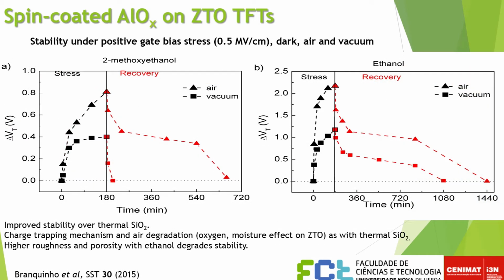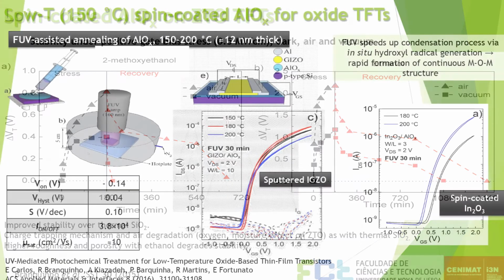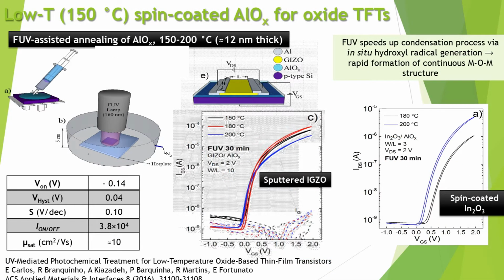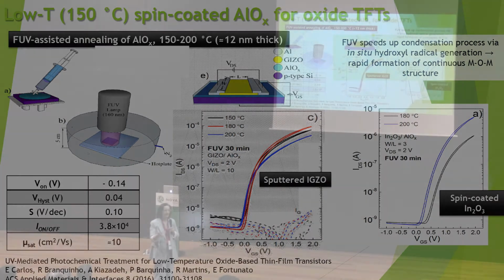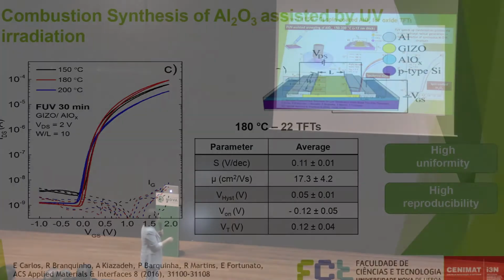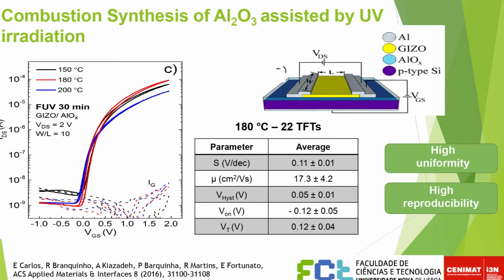And again, some stress stability with the devices, and more recently, by combining the combustion synthesis with the use of UV radiation, because we need to avoid the heating process. So in order to compensate the heating process, we use another source of energy like UV radiation, and we are able to build the devices at 150 degrees, which is quite good, since we are able to use this, for example, on flexible substrates.